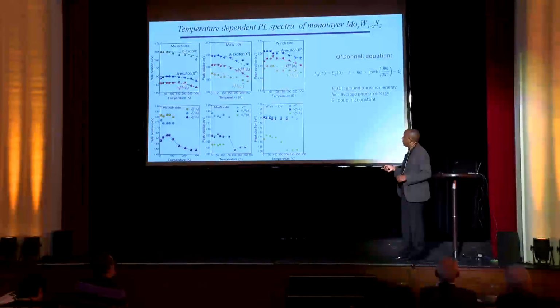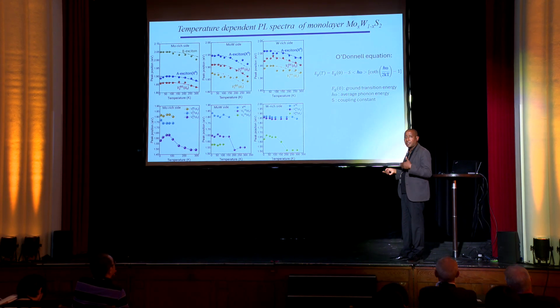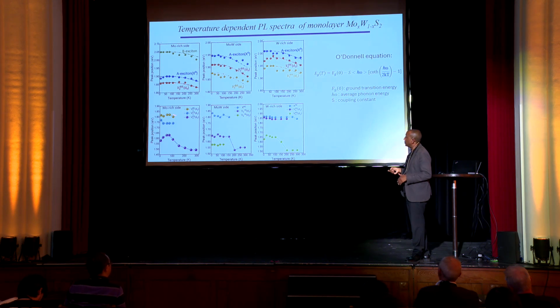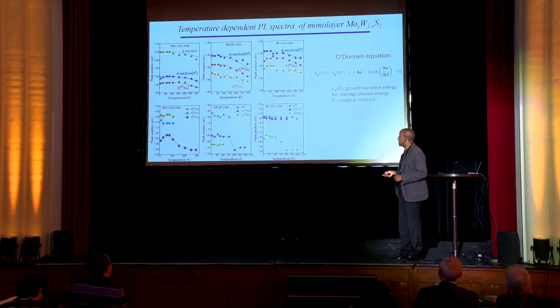However, you cannot do that for these other 3 peaks. So that gives us another confirmation that the 3 peaks are related to exciton-related excitations, whereas these are not. We cannot fit this with this equation, so they're vacancy-related peaks.